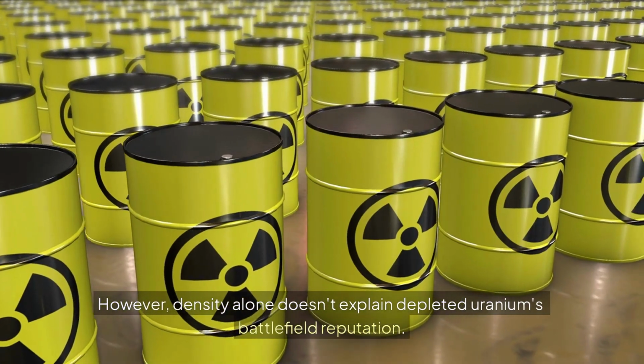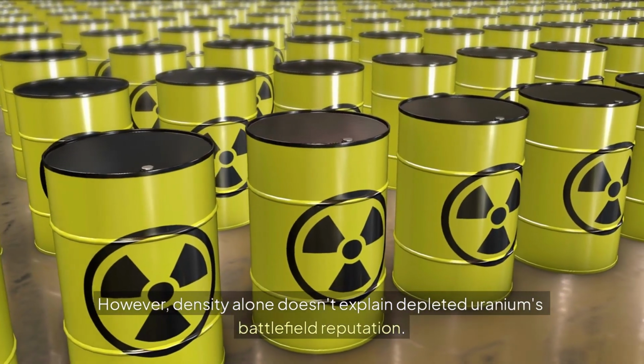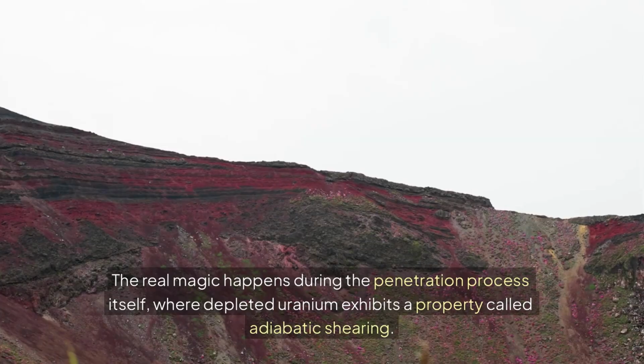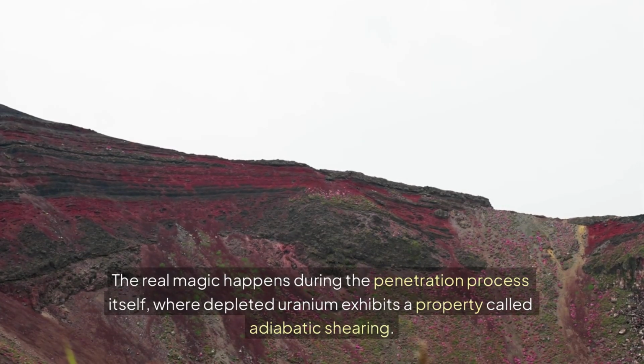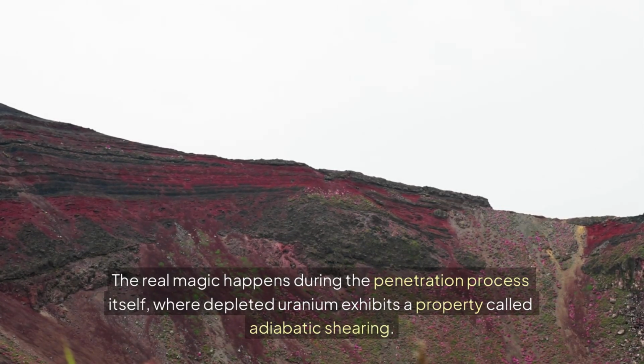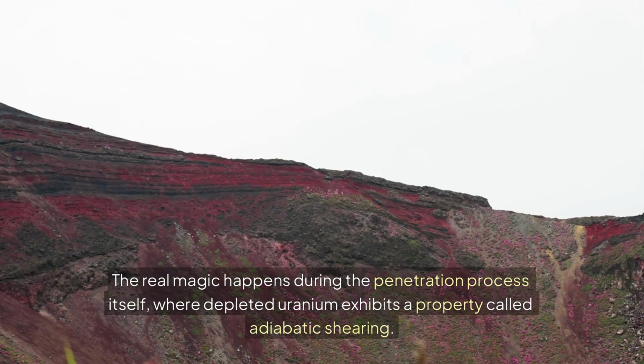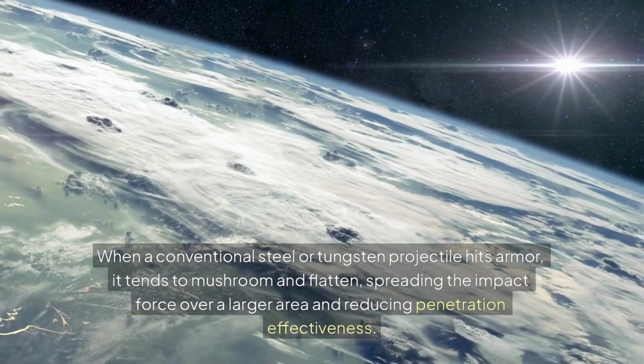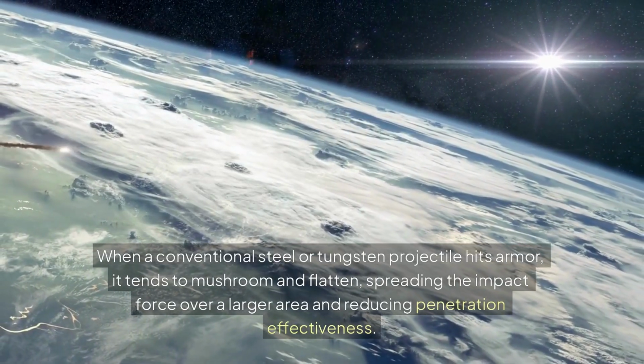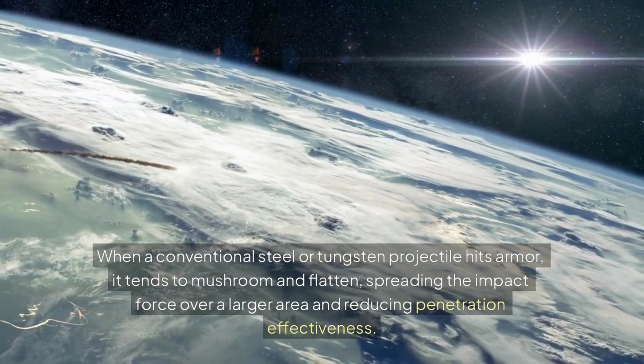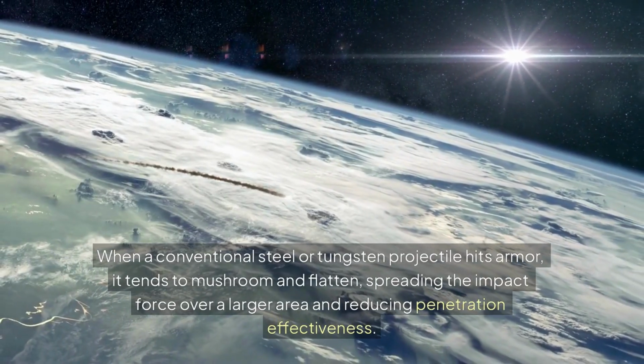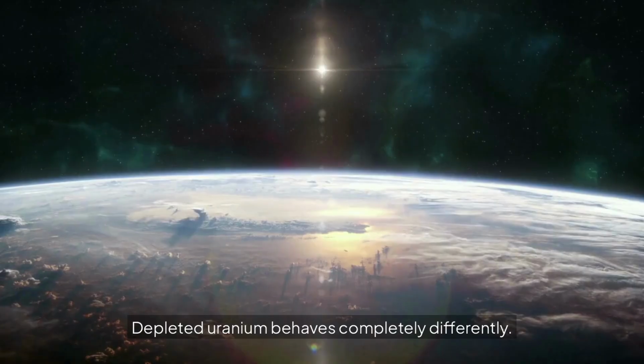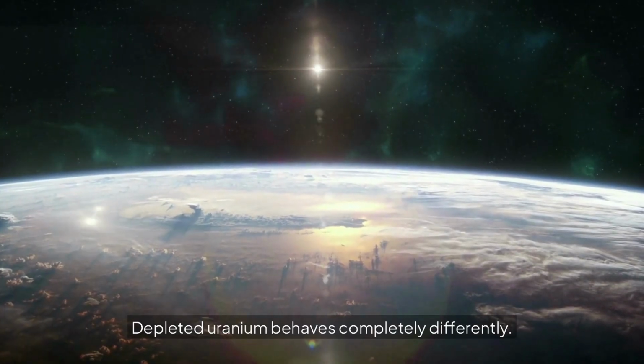However, density alone doesn't explain depleted uranium's battlefield reputation. The real magic happens during the penetration process itself, where depleted uranium exhibits a property called adiabatic shearing. When a conventional steel or tungsten projectile hits armor, it tends to mushroom and flatten, spreading the impact force over a larger area and reducing penetration effectiveness. Depleted uranium behaves completely differently.